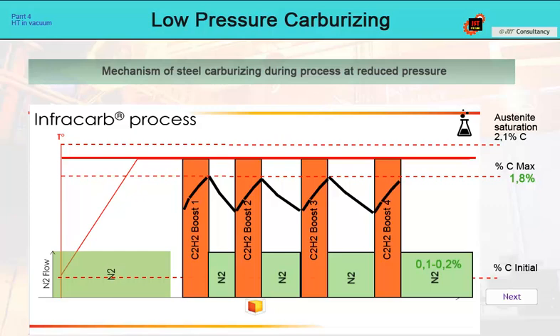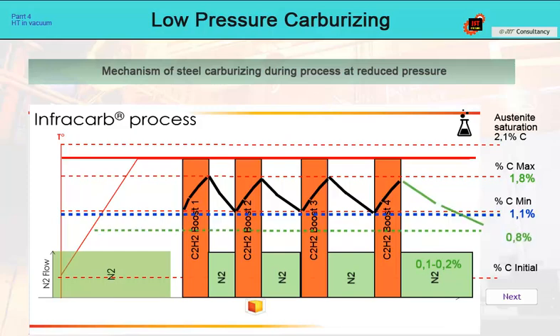As the carbon content in steel increases with each pulse, the gradient of carbon in the diffusion profile of the layer gradually decreases. Therefore, the diffusion segments are extended in each subsequent step, so that at the end of the diffusion period, the carbon content is around 1.1%. Only the last diffusion period serves to reduce the carbon content to a eutectoid amount, to 0.8%.